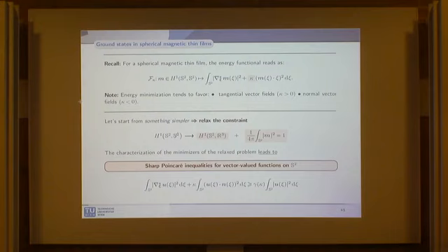But for kappa less than 0, we were able to say many things. And the idea was really simple, which was to relax the constraint. Instead of using classical penalization techniques, we relaxed the constraint: instead of assuming that m takes values on the unit sphere, we just assumed that the L2 norm of m is equal to 1. And then we were looking for sharp estimates, sharp inequalities of this kind, in such a way that we could find sharp lower bounds to the energy level. And this asked for